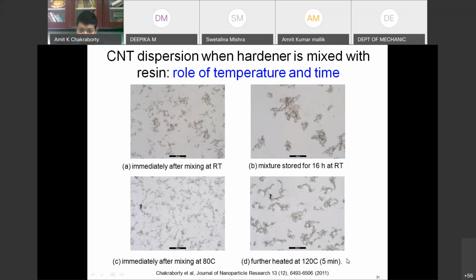Again, you see, as we heat at 120 degrees Celsius, even at 5 minutes, we see some agglomerate formation. See, these black particles are agglomerating. And even immediately after mixing at RT.